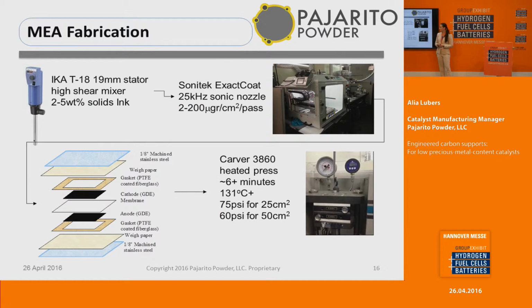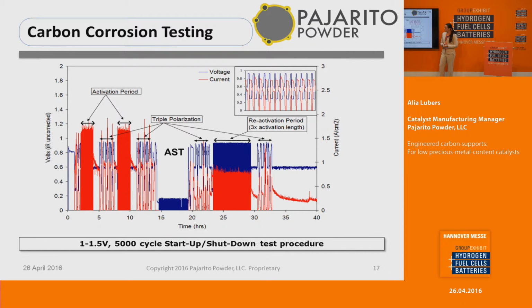So our partner sent us back platinized support so we could test it in-house. We use high shear mixing to develop our catalyst inks. We spray our GDEs and use a heated press to synthesize a 7-layer membrane electrode assembly. Our main evaluation for these types of materials is a carbon corrosion test, where in the beginning of the test we activate the catalyst, and then we have 5,000 cycles of start and stop simulation. We then activate it after our corrosion testing and have an end-of-life test after reactivation.